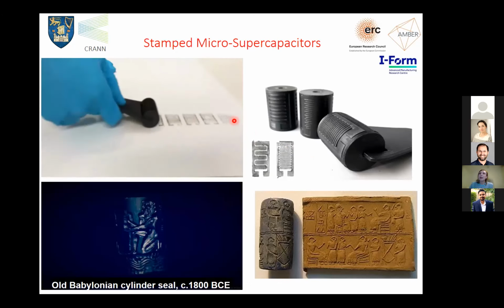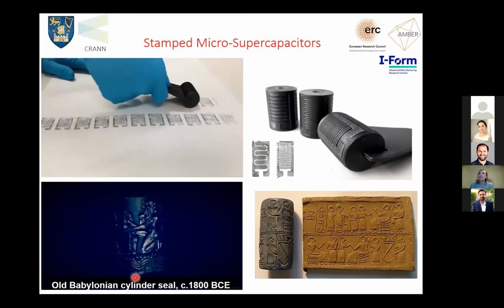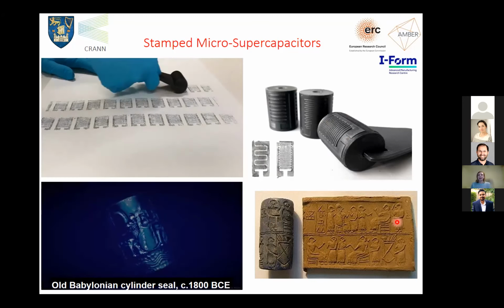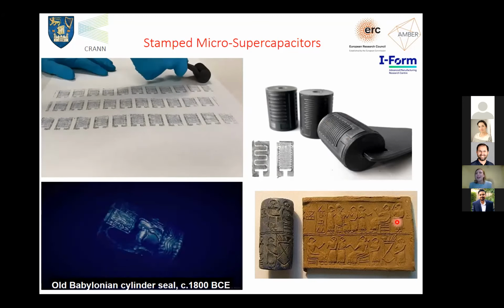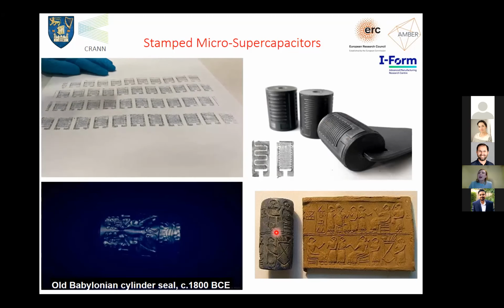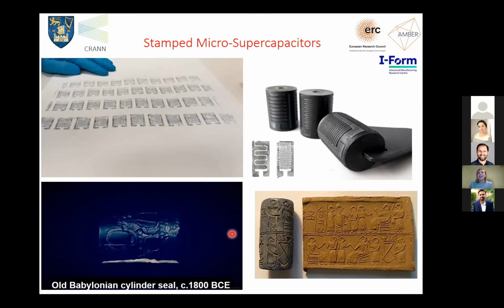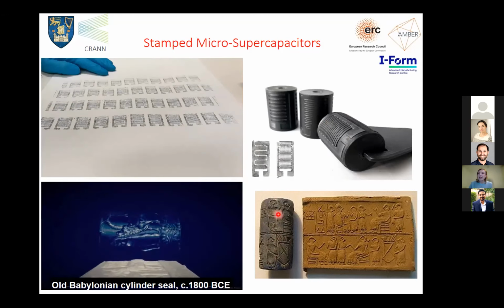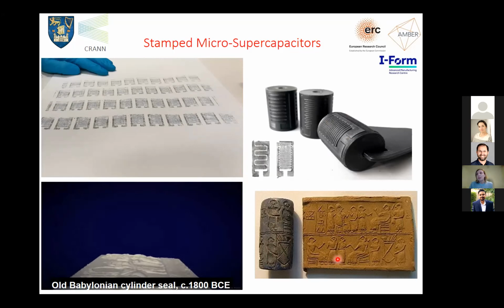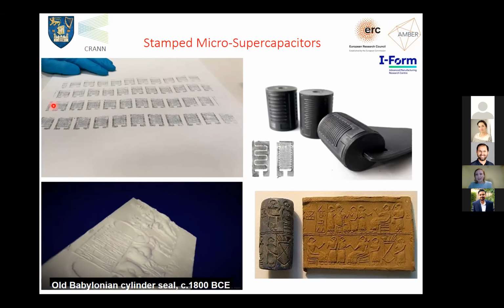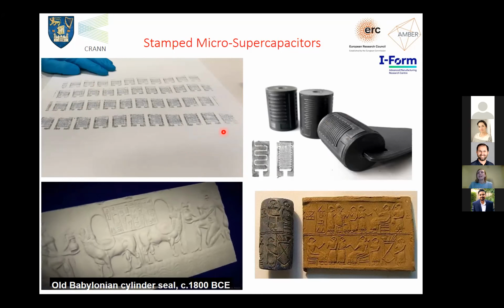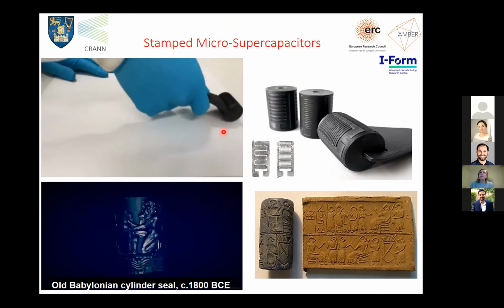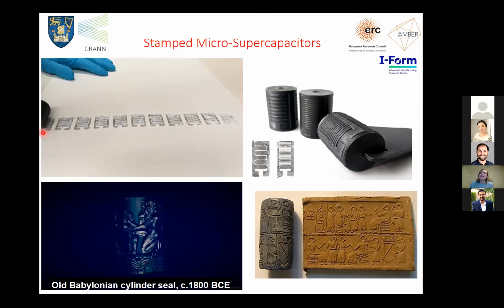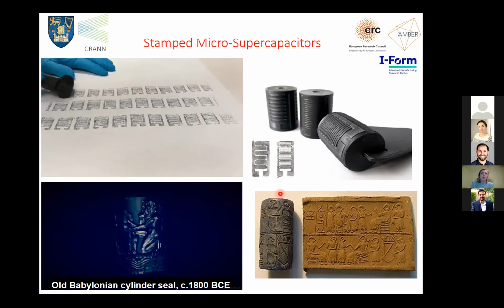And this is another step, because what we did also was to print rolls. We basically did what the Babylonians did back in the 1800s BC. They used this methodology to print down their art. So they were inscribing their art on the rolls, and then they were just rolling away. And this is pretty much what we did, but with supercaps and using MXene inks. That allowed us to print several tens of devices in one go. So it's a very easy way to do fast prototyping.